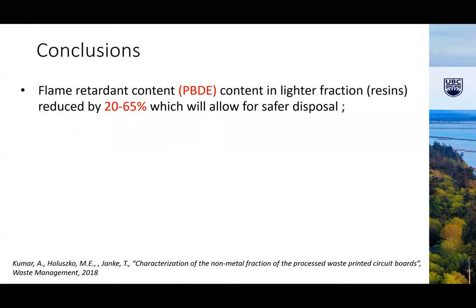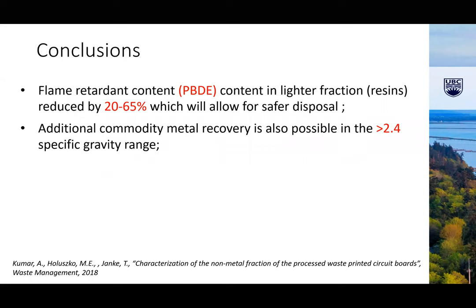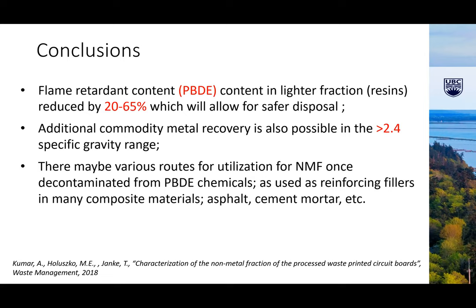Flame retardants content in lighter fractions of resin was reduced. So again, by sorting this material, we can actually reduce the content in some fractions versus others. However, comparing to the limits, none of the fractions were above what's required for landfilling in British Columbia. But looking forward into stricter regulations, we should rather do a better job than just relying on the limits of the landfilling, even though it's very important, because companies will not be allowed to dispose if they don't meet those limits.